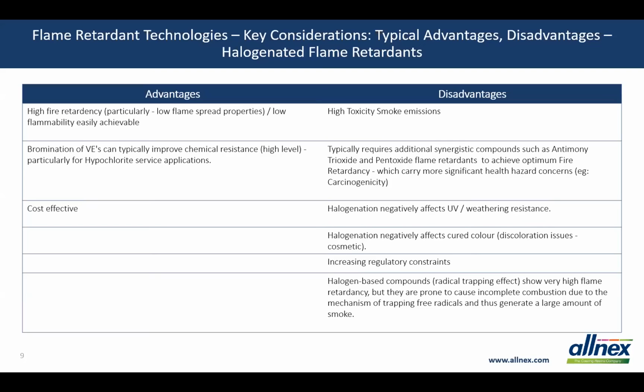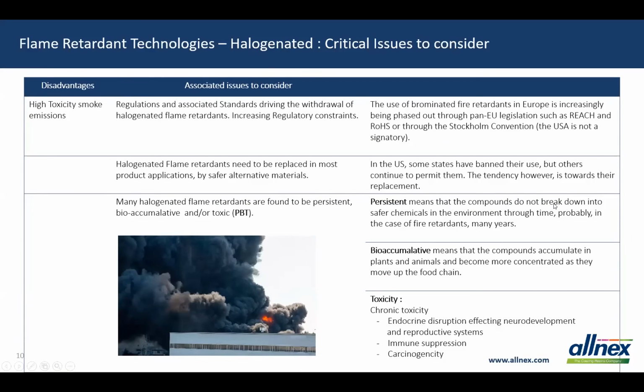These materials also require additional synergistic compounds, other additives basically, such as antimony trioxide, generally combined with halogenated materials to achieve optimum fire retardancy. So on their own, they're not as effective. They're very effective in combination with antimony compounds. However, these other synergistic compounds, such as antimony trioxide, have associated carcinogenic properties, which is another problem. So these concerns have largely been driving the withdrawal of halogenated flame retardant materials in many areas around the world and replacement with safer non-halogenated alternatives. There are increasing regulatory constraints specifying the use of non-halogenated flame retardants, and the fire performance properties of halogenated materials will not comply with quite a few, many fire standards which have been written for many specific industry applications around the world these days.